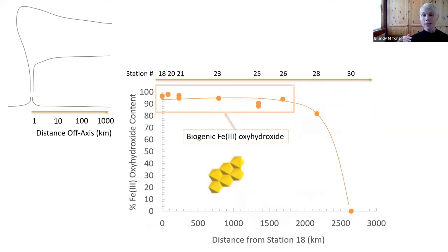So bringing that back then to the big hydrothermal plume at the East Pacific Rise, what we think is happening is the iron 2 is coming out of the vent. It's mixing with background seawater, which is oxygenated. And very likely there's a pretty rich ecosystem in the vicinity, because there's a lot of organic carbon that's being taken up by these materials as they precipitate.